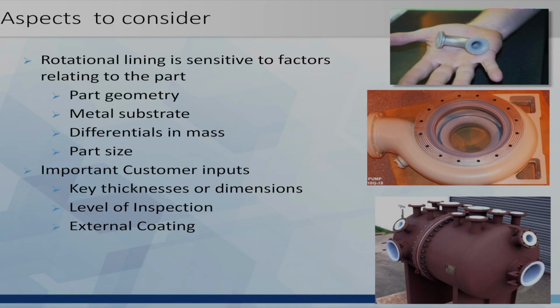Sometimes there are differentials in mass where we can get different temperatures of the part because there's a heat sink, and we will get different thicknesses of the liner. So just several things to consider when we go to design the process for unique parts. The part size, we typically don't like to go below 1.5 inch. And in terms of the large size, it just has to be able to fit in the ovens of a given supplier.